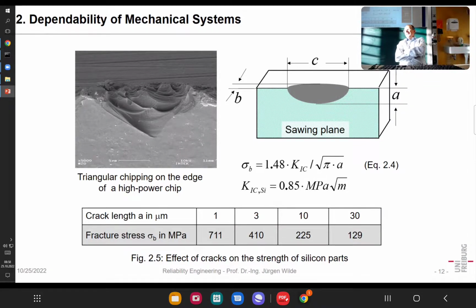That means having something like a crack or even just a scratch on the top will degrade the strength. It's similarly important for glass, for instance, window glass. How is glass separated when you have a big sheet and make a smaller sheet? How do they do it traditionally? They scratch it and then they bend it over an edge, yes? And then from that scratch on, it will break, and it will break really easy. That's the way, and that's the same principle.